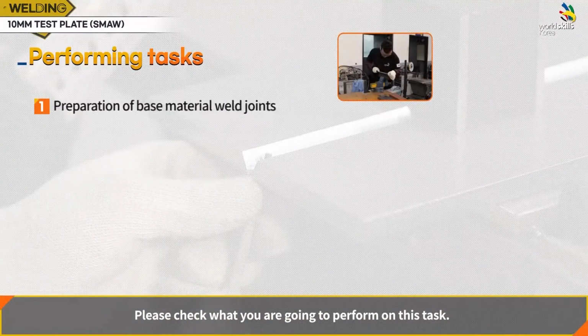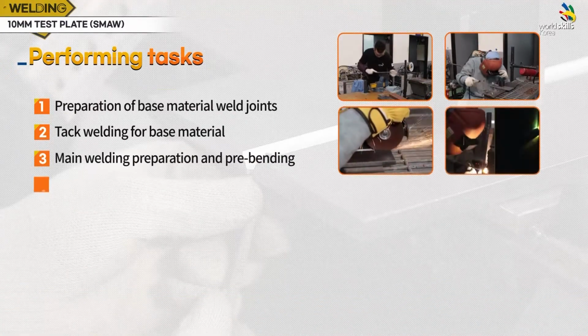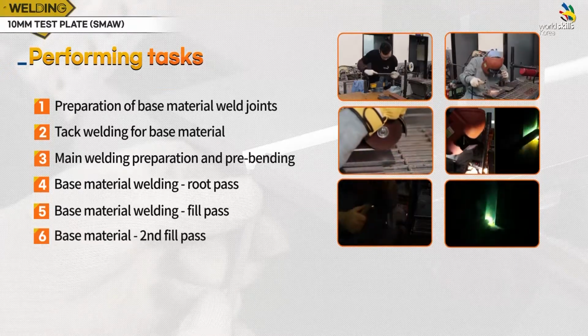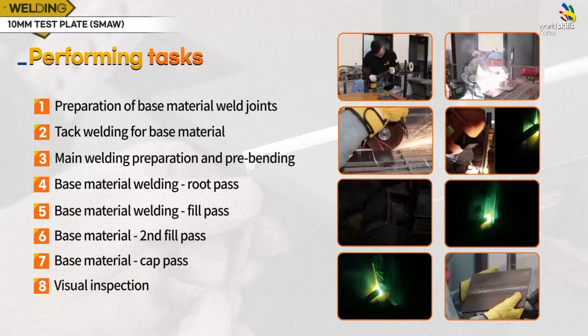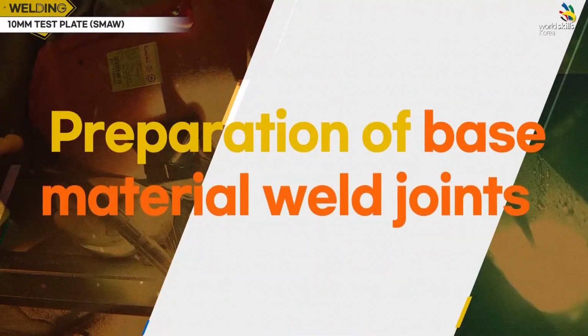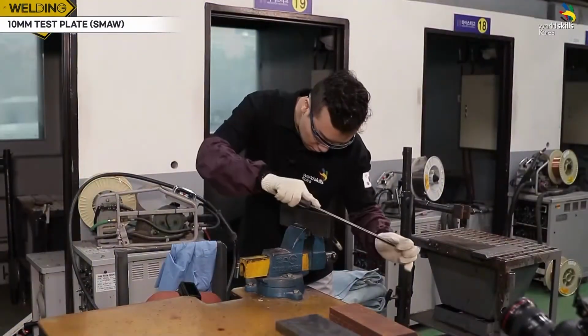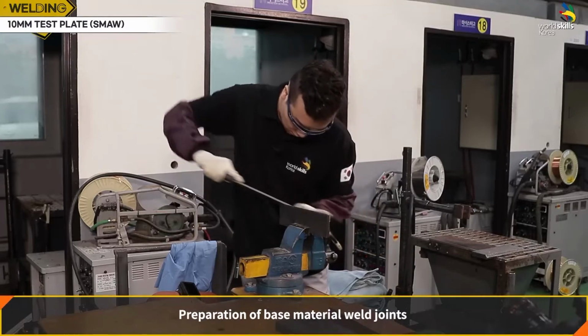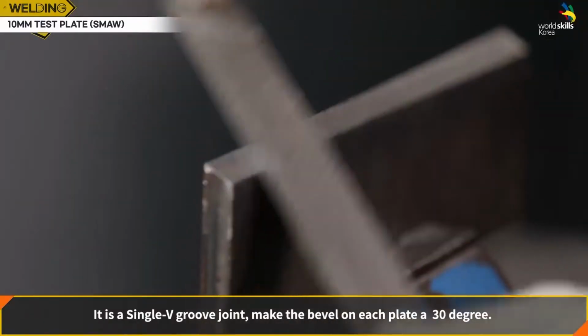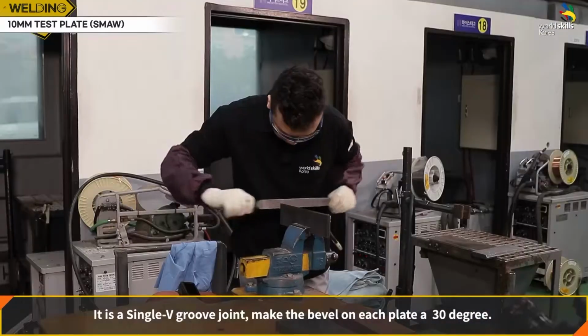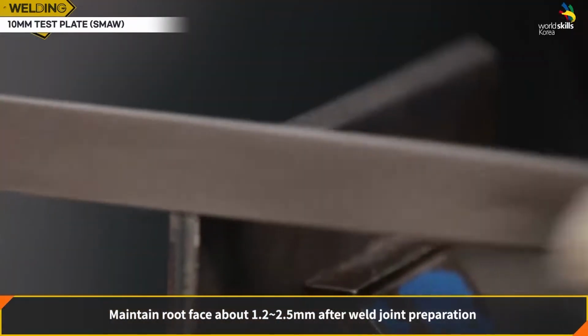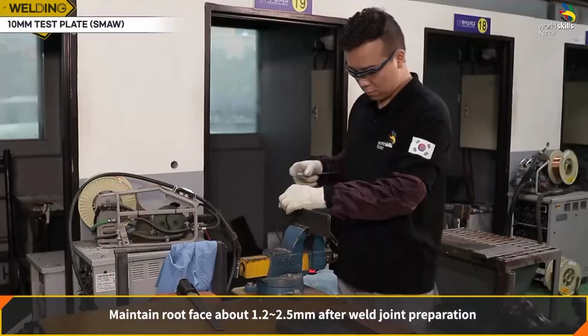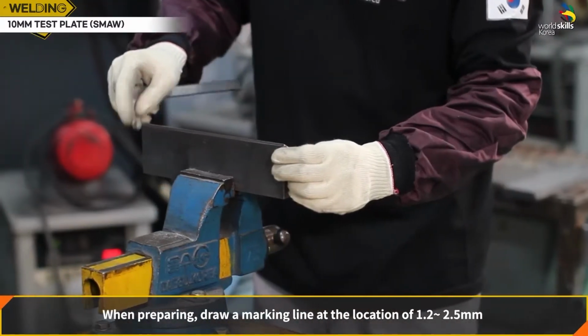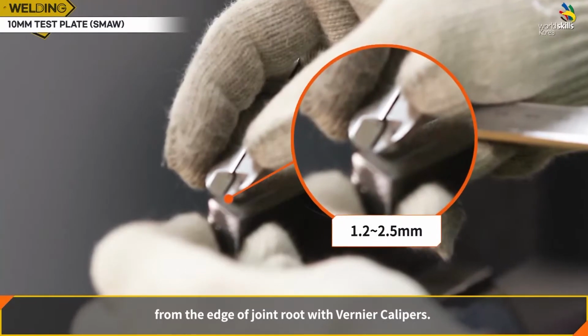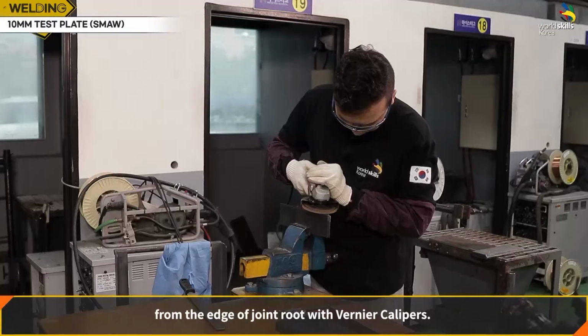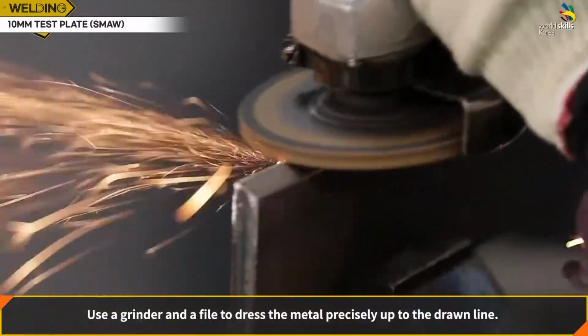Please check the tasks to perform. Here is what to do. Preparation of base material weld joints. It is a single V-groove joint. Make the bevel on each plate 30 degrees. Maintain a root face of about 1.2 to 2.5 millimeters after weld joint preparation. When preparing, draw a marking line at the location of 1.2 to 2.5 millimeters from the edge of the joint root with vernier calipers. Use a grinder and a file to dress the metal precisely up to the drawn line.